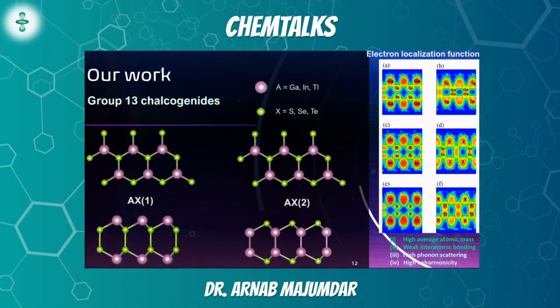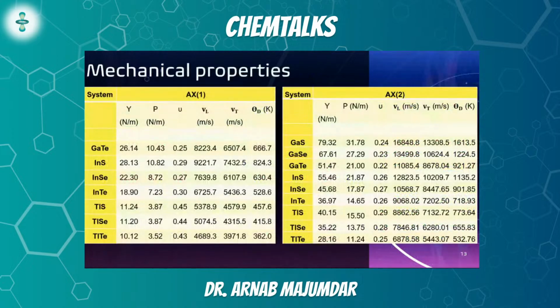And there you go. If you compare the different columns for the same corresponding materials, you'll see that the Young's modulus, the shear modulus, the Poisson's ratio, the velocities, and the Debye temperature, which is very important, the last column, for AX1, they're much lower compared to the values of AX2.